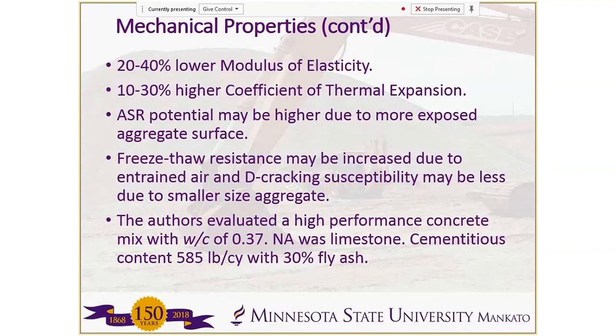On the positive side, the freeze-thaw resistance may actually be increased when using recycled concrete because you already have some entrained air within the aggregate itself. Also, when you recrush this to a smaller size, D-cracking susceptibility may also be less. ASR potential may be higher with recycled concrete. So in general, you can see that most of the mechanical properties seem to show that recycled concrete aggregate would not perform as well as conventional aggregate concrete.